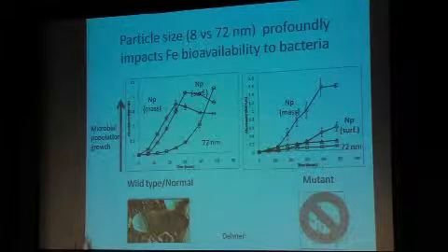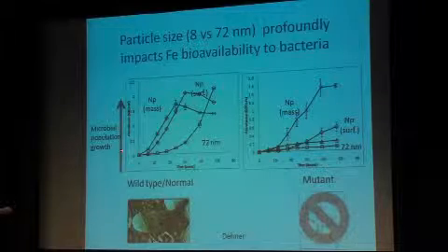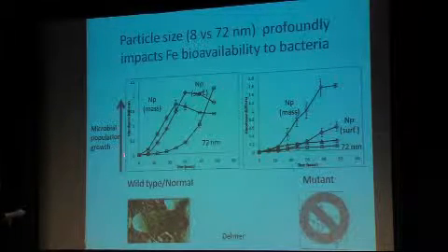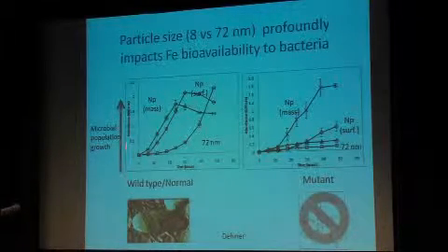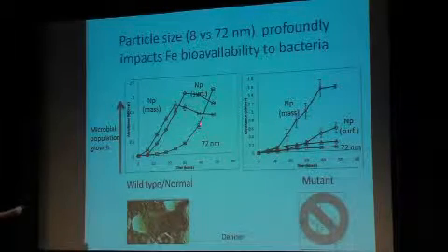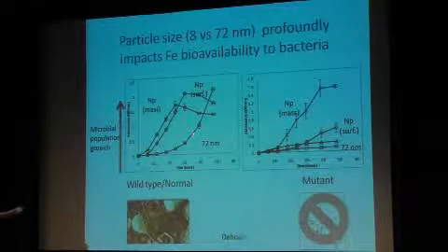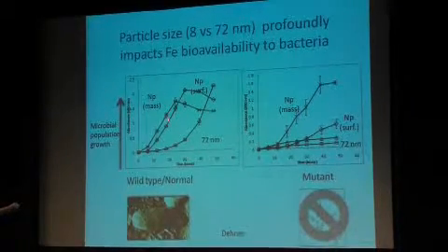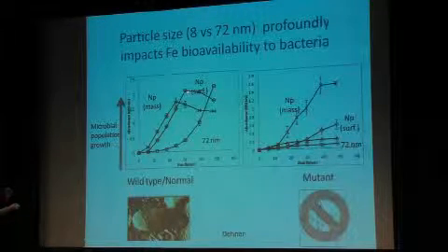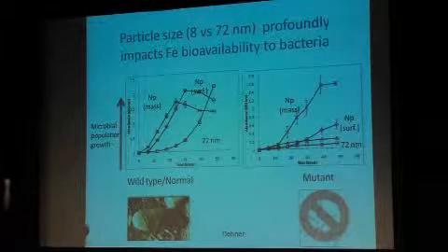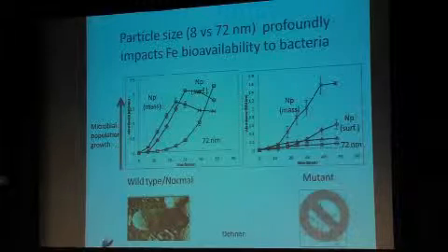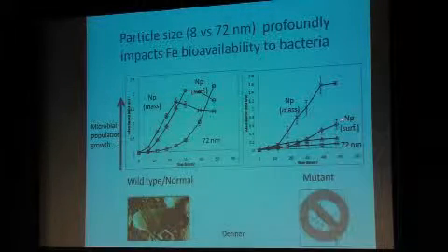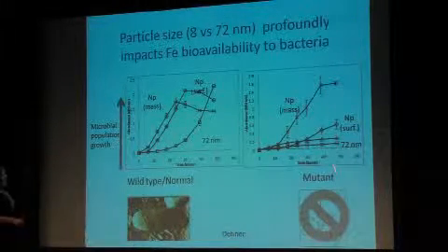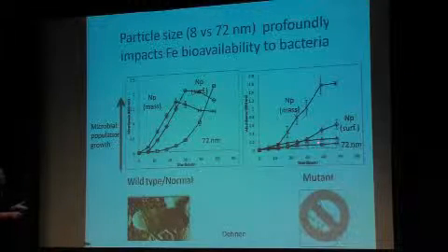I showed you the dissolution there. This is the growth, the microbial population growth. These bacteria can only grow if they acquire iron. Grown on 72 nanometers, it takes them a long time to start growing, although eventually they do grow pretty well. If you've got nanoparticles, they start growing much, much better. And they grow a little differently depending upon whether you normalize the experiment to the same mass or the same surface area. Over here, we grew the mutant, which can't produce this siderophore.